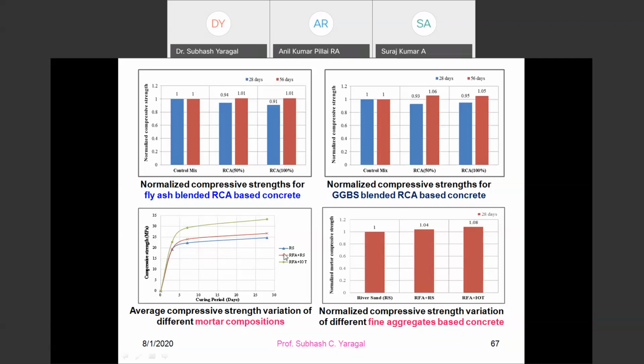Now, what we have done, river sand, you have the strength here. We have used recycled fine aggregate along with river sand. Now, why we have done this hybrid? The recycled fine aggregate, which is taken from construction and demolition waste, has the problem of water absorption. Anything less than 300 micron, that is 300 micron and 150 micron, has the problem or behaves like clay, and therefore we got rid of those two fractions. So this recycled fine aggregate does not have 150 and 300 micron sizes. Those are provided by river sand. I'm saving the other fractions here.